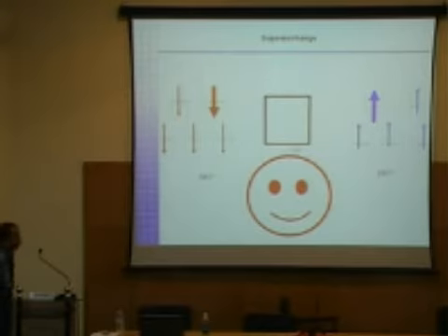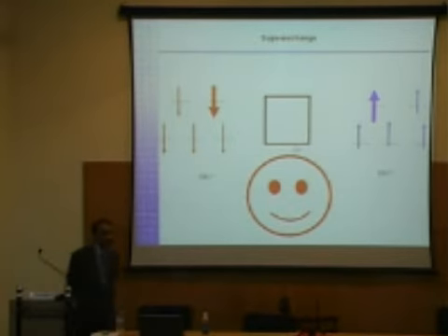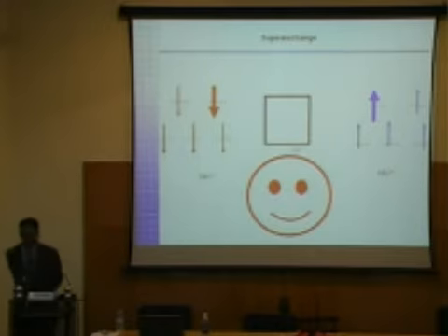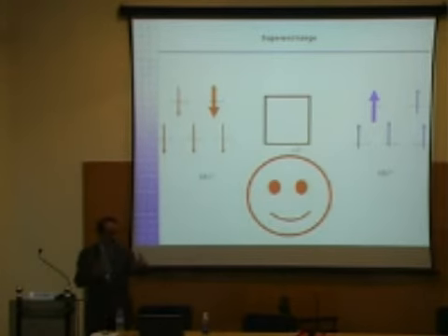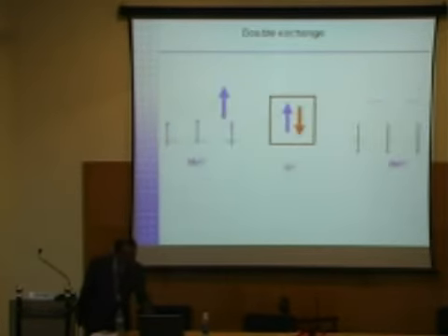In fact, I have examined hundreds of manganese 3+ compounds, and I have yet to see any manganese 3+, oxygen 2-, manganese 3+ showing any ferromagnetism. So typically, we only see antiferromagnetism. Of course, one can apply these rules for different cases. You can sit down near a drawing board and look at different types of ions or play the same game and see what type of magnetic ordering you might be able to see. And most of the time, you are right. There are exceptions, of course.